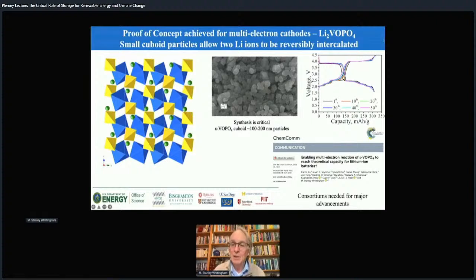But there are still challenges here. In this region here, we see the bumps and the slopiness. This is some lithium ordering, but this is single phase, extremely high rate in this region. But up here, this is now a two-phase region between VOPO4 and LiVOPO4. So this tends to be somewhat more sluggish. So we have to modify this to make it more reactive so we can get the high rate reactions going on. So we're studying that at the moment.